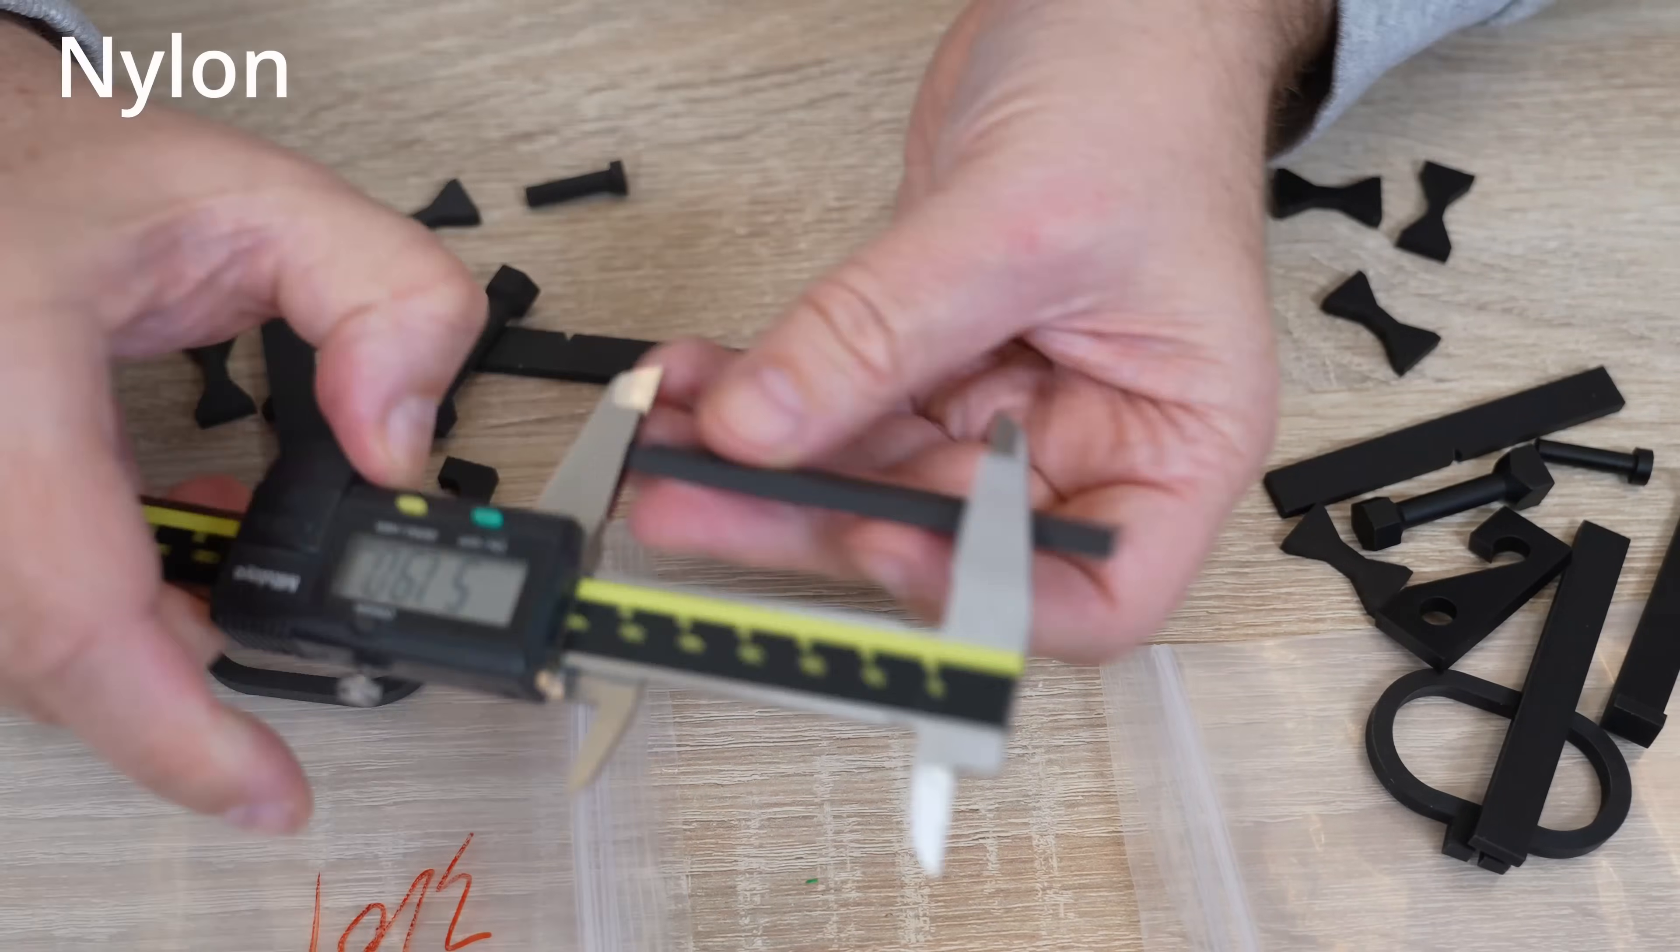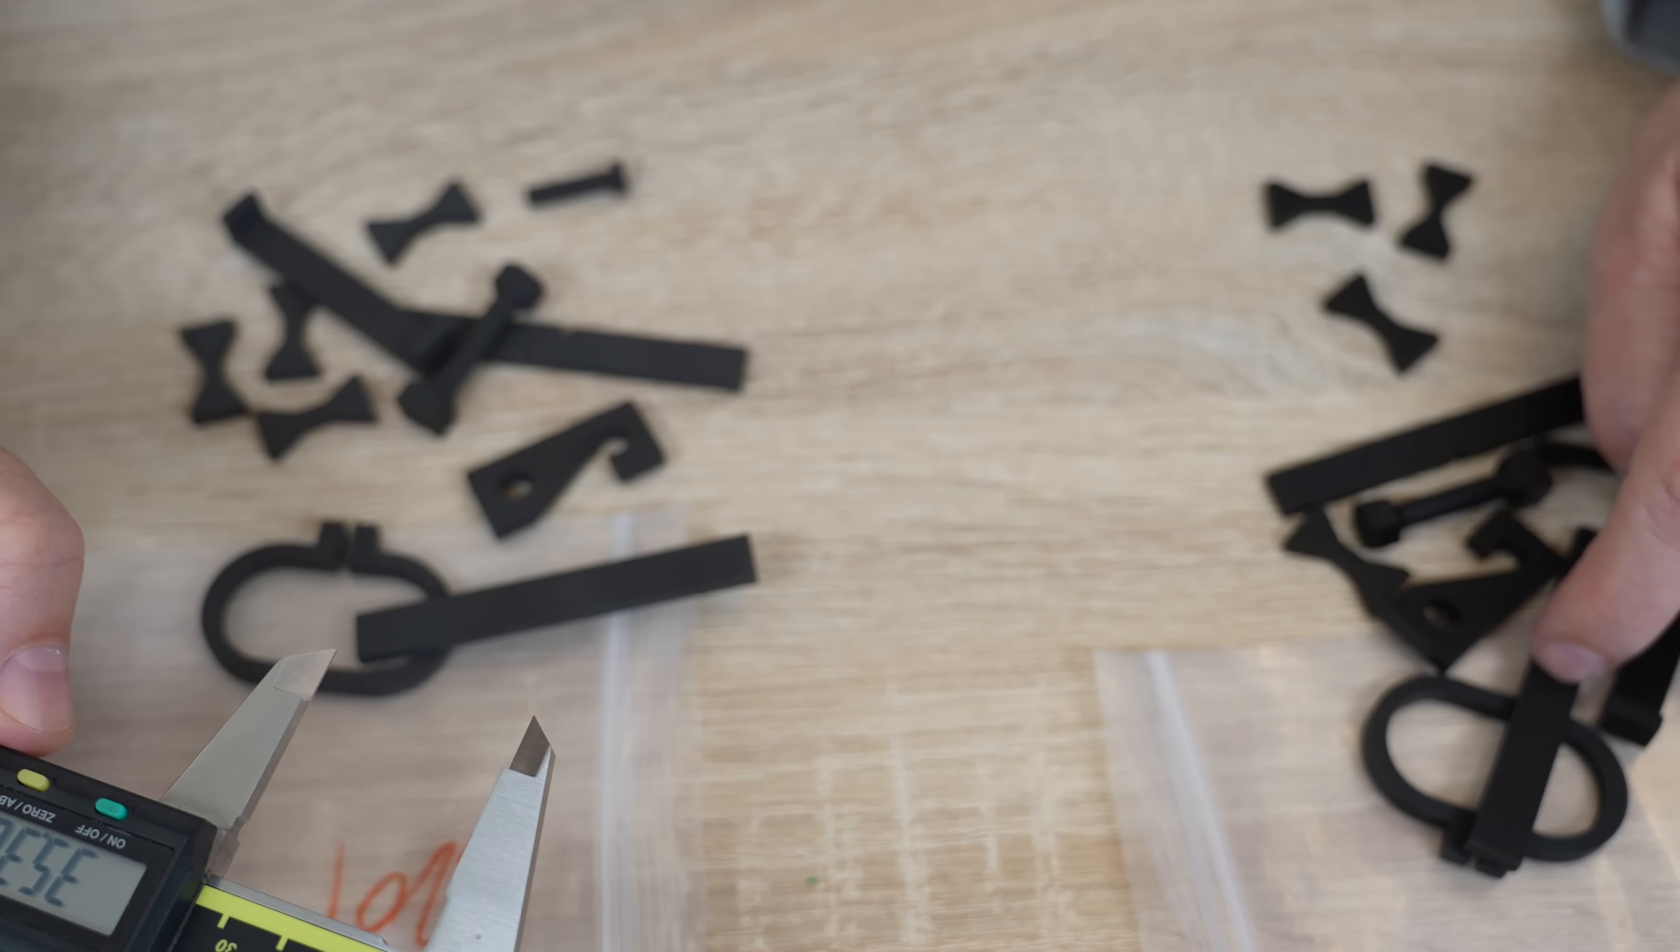Just quickly to check the dimensional accuracy, the design length is 80 millimeters here. 80.06, there is no elephant foot here, and hook in x and y direction, wow, 39.00, 17.00, really accurate. And now the nylon: 80.17 so a little bit bigger and no, there is no elephant foot here neither, and the hook 39.06, 17.09. So a little bit bigger but this black resin really has great dimensional accuracy.